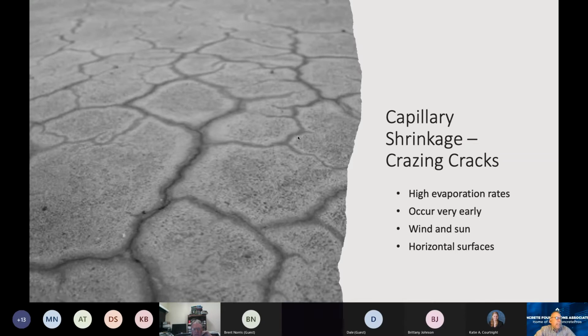There's another nature of cracking that happens immediately. And this is probably one of the more problematic cracks from an aesthetic perspective and from an owner satisfaction perspective. It's called crazing cracks. It's caused by capillary shrinkage. And so if you can imagine this floor slab, we've just placed the concrete, we've got it all floated off, it's got its bleed water that's risen to the top, and then we're in Colorado and the winds are blowing and the sun's out there and it's baking that concrete.